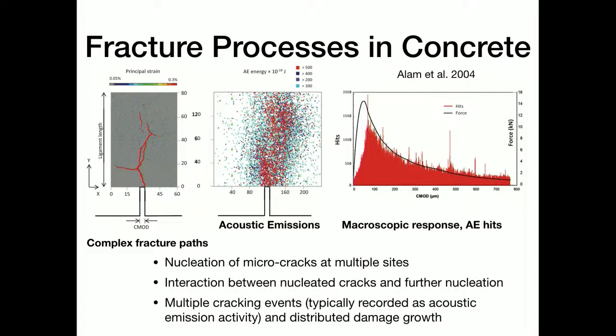And this is also observed in the macroscopic response. If we see the AE hits, you see a lot of activity before the peak load is reached, and even after the peak load there is a significant amount of activity. So nucleation of microcracks occurs at multiple sites, and as the material is heterogeneous, its fracture behavior is statistically distributed. This makes it a very complex system to analyze.